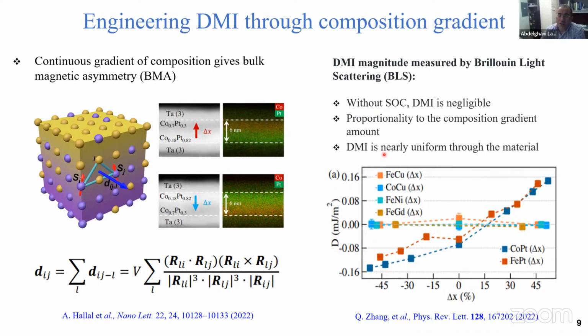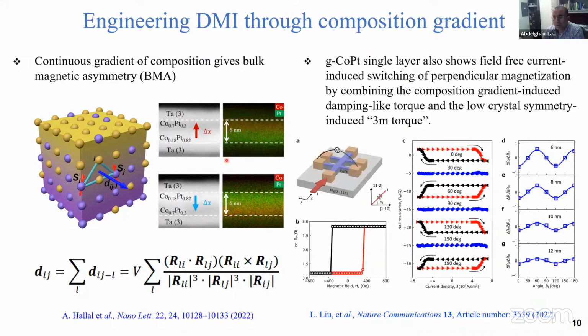And then in addition, this is a single layer. So just by changing the composition while growing the material, you can create this DMI. It's not the case of a multilayer, where you need to create a layer of another ferromagnet and heavy metal to increase DMI. I also just want to mention that this system, in particular cobalt platinum, usually has